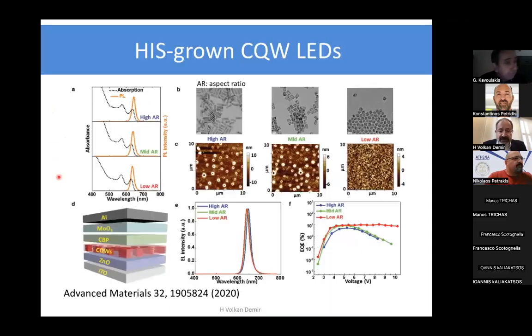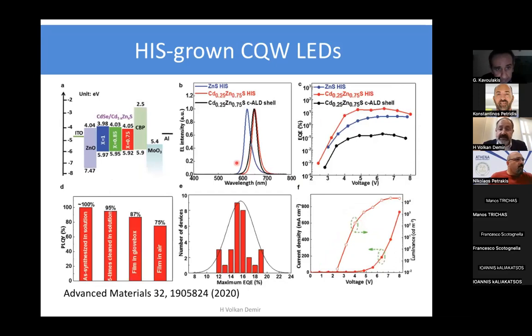To be able to reach this level, we had to understand also the lateral structure, because in our synthesis, we can carefully make high aspect ratio, rectangular versus squarish structures, and we have good control to do that. What we found is for these electrically driven LEDs, one has to go to low aspect ratio structures, and then we need to take that and again, look into a particular shell structure to achieve the best performance.